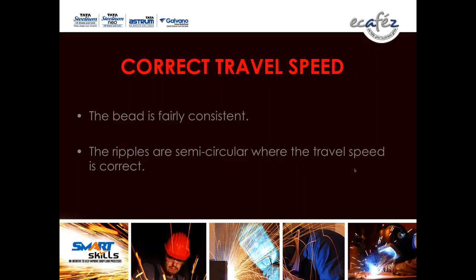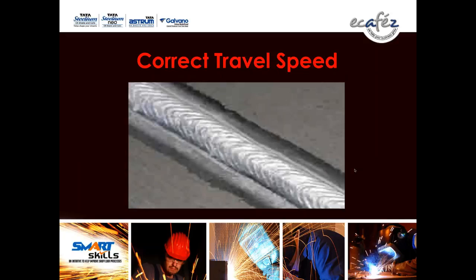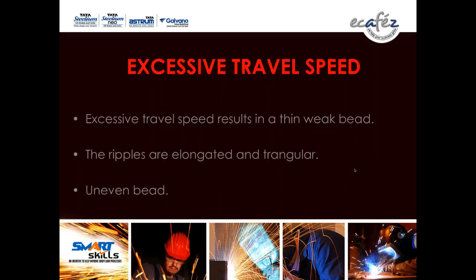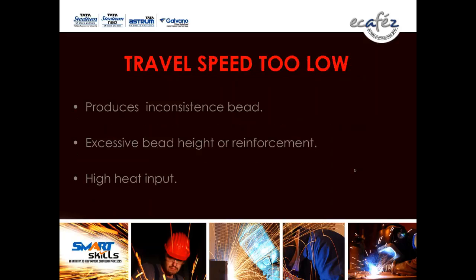Correct travel speed: the bead is fairly consistent. The ripples are semicircular where the travel speed is correct. See the pictorial view of correct travel speed, unique welding bead. Excessive travel speed results in a thin weak bead. The ripples are elongated and triangular. Uneven bead will occur. Travel speed too low produces inconsistent bead, excessive bead height and reinforcement, and high heat input, which will affect the welding properties.